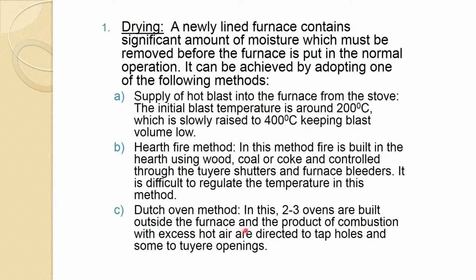So, ovens are built outside the furnace and the product of combustion with excess hot air are directed to tap holes and some to the tuyere opening. So, essentially what you are getting is a hot product of combustion from this, and with the excess hot air which is directed from tuyeres or tap holes opening, you get the temperature the way you get it in the first method. So, by adopting one of these methods, one can remove the moisture from a new blast furnace or relined furnace, which is an essential step